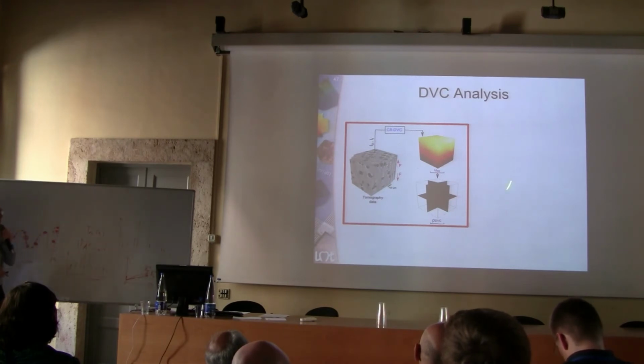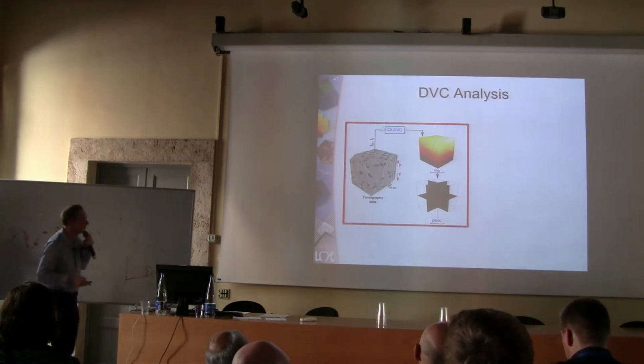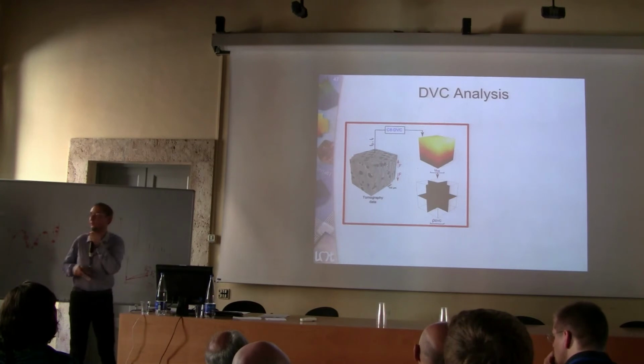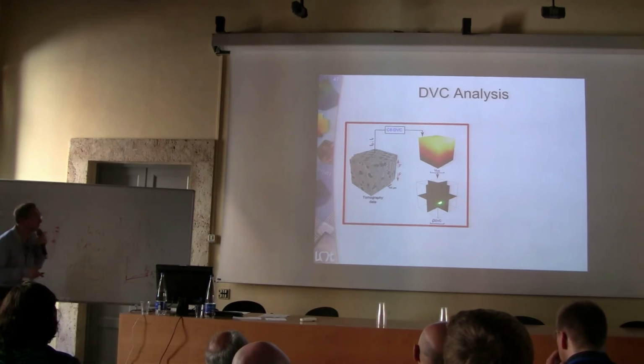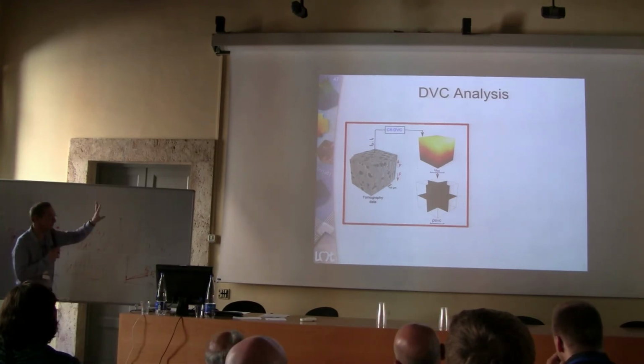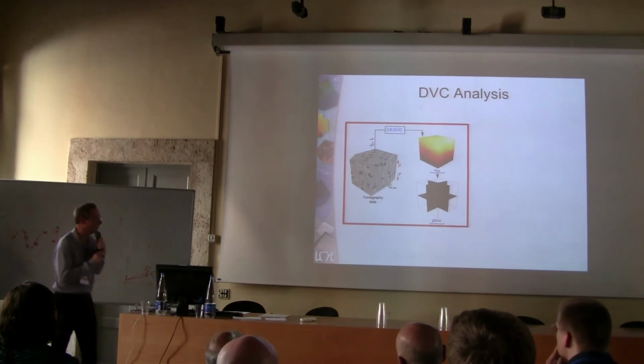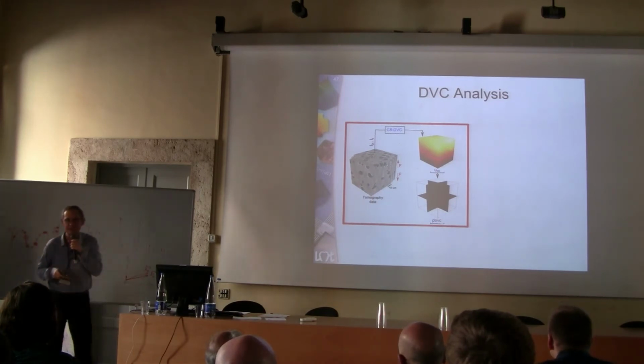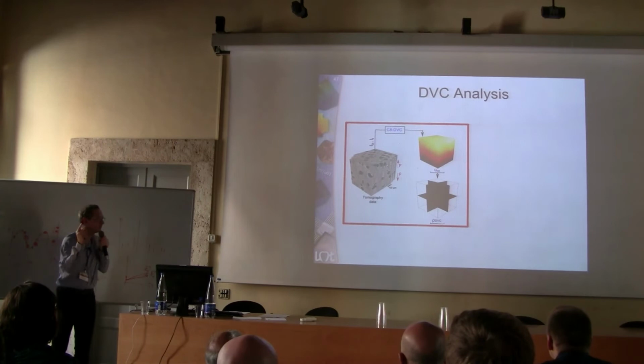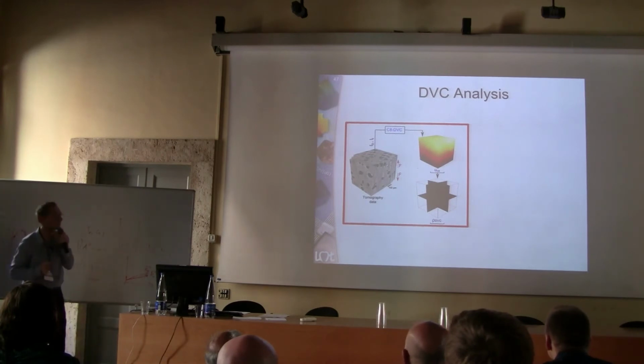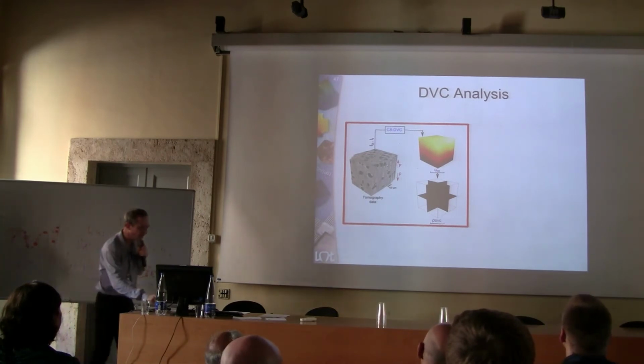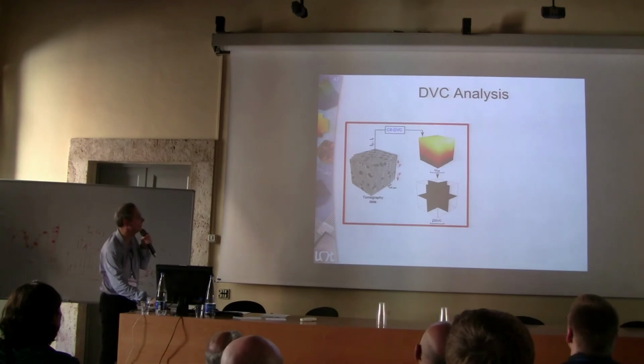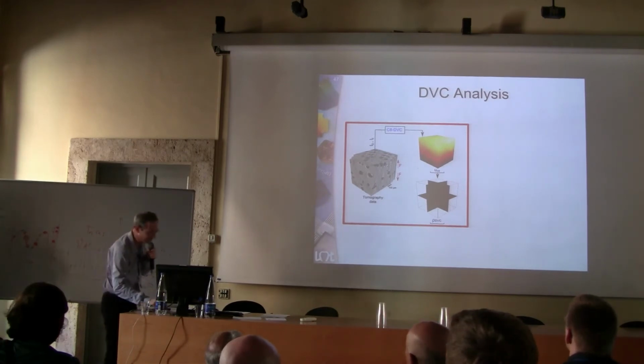And here you have an ortho slice of the gray level residuals. Unfortunately, probably none of you will see that - for you it's probably black everywhere. Actually, it's not exactly the case, as we will see, around the nodule to matrix interfaces. I'll come back to that a little bit later. Actually, I anticipated this problem.